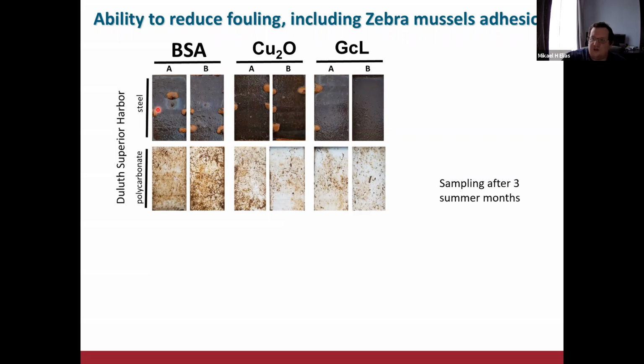You can see steel. So this is a control with a protein with no activity. This is the coating with copper, and this is the coating with our enzyme disrupting microbial signaling. And so, after 3 summer months, you obviously see less corrosion with our enzymes. This is polycarbonate as a substrate. Polycarbonate is a really good substrate for biofouling and for the adhesion of mussels. Here there was no mussel in the Duluth Superior Harbor.